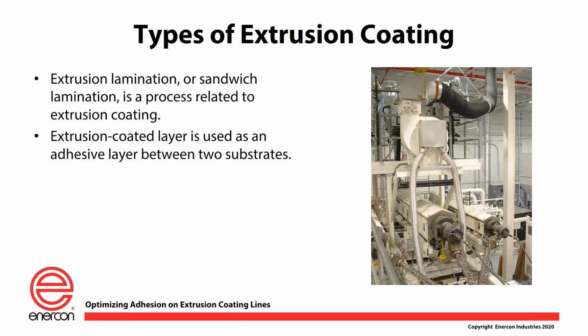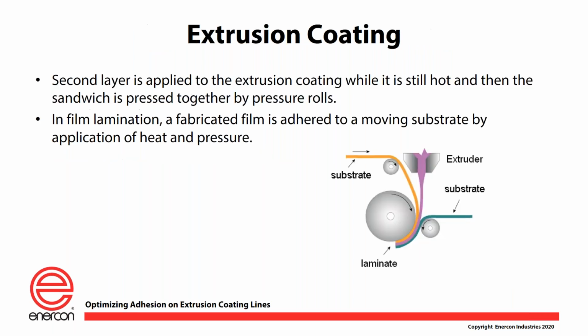So to get a little deeper into this, we'll look at the next slide and we'll see a bit of an overview of what this looks like. In this picture, you see the main substrate, that orange substrate, coming into the chill roll and the nip area, and you see where the extruder is. That extruder is taking these polyethylene pellets, melting them, and applying them into this nipped gap area so that the substrate product actually gets coated with that polyethylene extrudate.